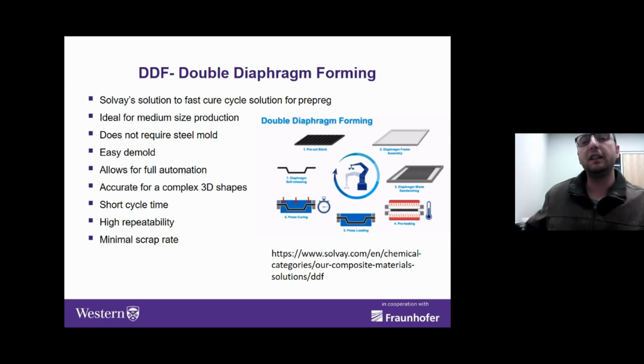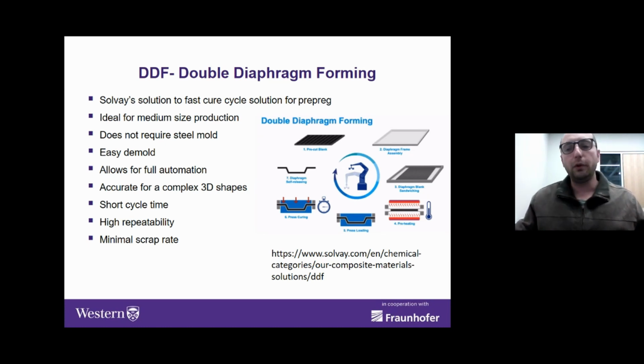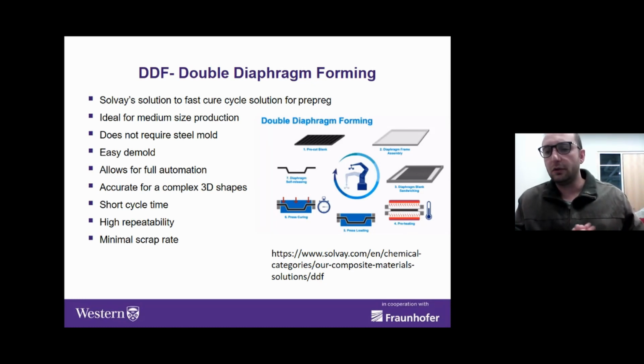And the beauty about this process is, and that's what we hear from a lot of companies about liquid compression molding in terms of the problems they envision, they say, okay, so you can automate everything, but how are you going to clean the mold? So you molded the part, great, now the mold opened, you took out the part, but you have all of that flash still glued in your mold, and now an actual person has to come and remove it before next cycle can begin. And this obviously makes cycles longer. In this process, this is not a problem because the pre-preg is in between two films, and the films basically act as a barrier between resin and the mold. So nothing sticks to the mold, so it's very easy demolding.